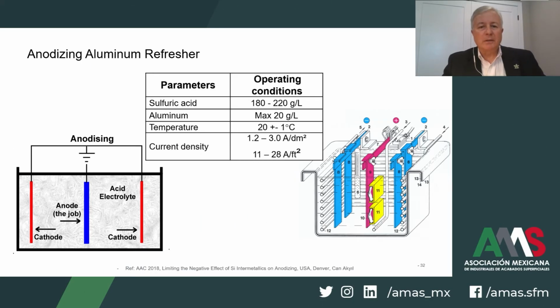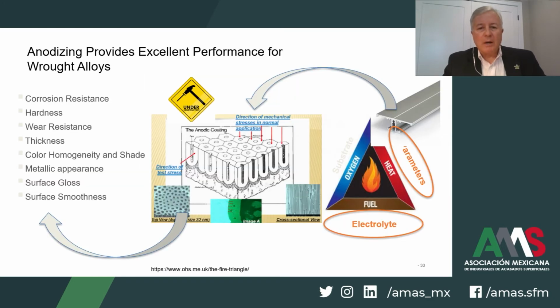When talking about type 2 or type 3 sulfuric acid anodizing, here are the typical operating conditions for the process of creating the oxide layer, shown on the screen. Wrought alloys are processed with relative ease in anodizing applications. Paying attention to the operating parameters and using the correct electrolyte chemistry will give you the desired properties in the resulting layer, a high quality coating. So excellent performance for the intended application when we talk about the hardness, wear resistance, thickness, color, stability, as well as the surface smoothness, amongst other properties.